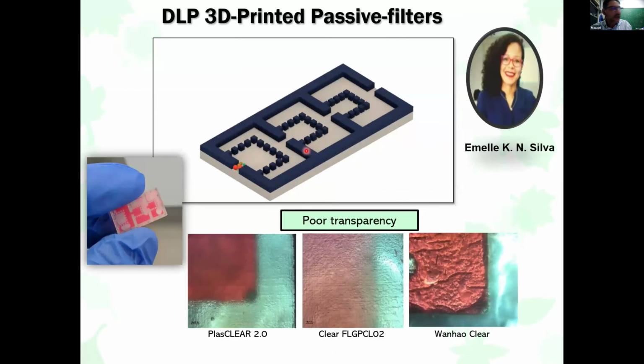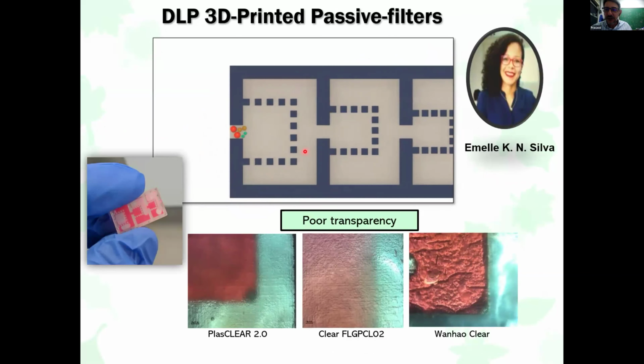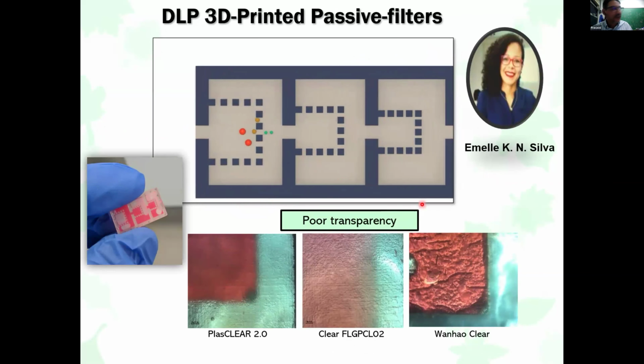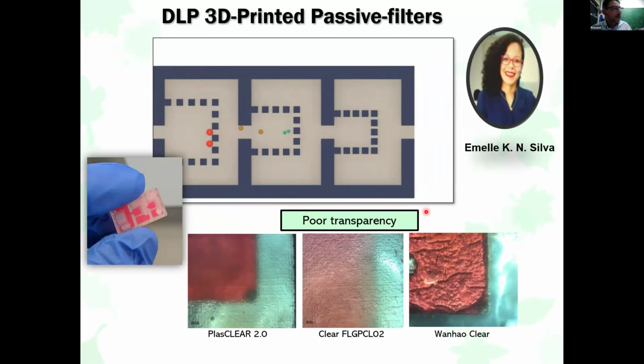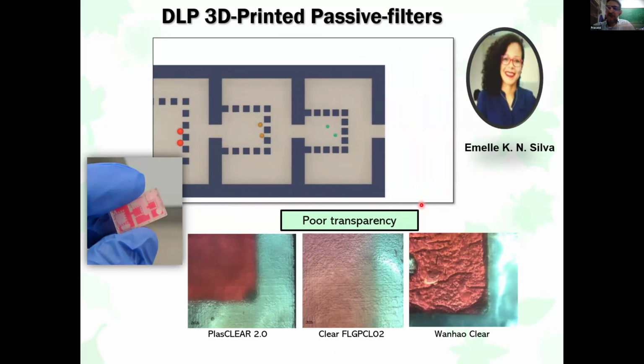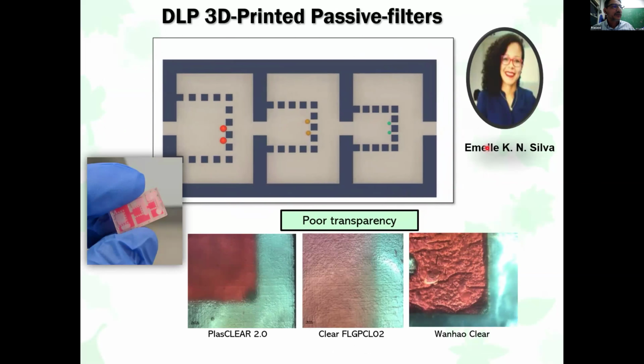So the first device we prepared using DLP printers was a cell sorter. We're interested in a device to separate different cells. So Emily worked on this device, and I was worried that we could not get a good transparency of the device. I expected a much better transparency in this DLP printed device than the FDM device. So this was one of the first devices that Emily printed.